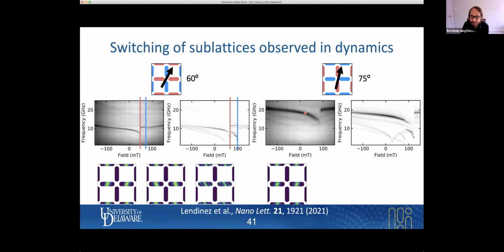This is cobalt iron on the horizontal elements, there's a step-down feature and then a step-up feature. And you can also see nicely that this step-down feature coincides with the switching of the permalloy, which is this faint line here. So again, I'm plotting here the horizontal elements. That's this mode before the switching occurs. So we see the tilt.